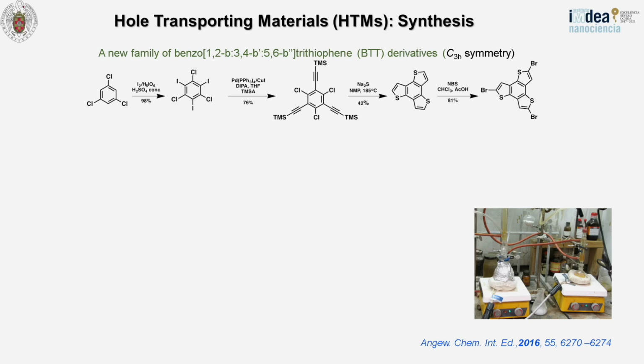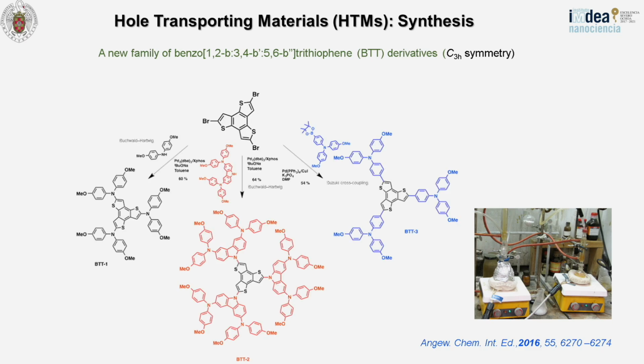Here you have the synthesis, which was very simple: a commercially available compound, an iodination reaction, and from here a palladium catalyzed Sonogashira cross-coupling reaction. This is quite a singular reaction at very high temperatures in which the formation of the thiophene rings occurs, and from here, just introduction of bromine atoms. So relatively simple, in 4 steps you get your central core, and from here it is possible to create a variety of hole transporting materials just by amination, Buchwald-Hartwig reaction. And here you have the BTT1, BTT2, and BTT3. That was the chemical protocol, okay?